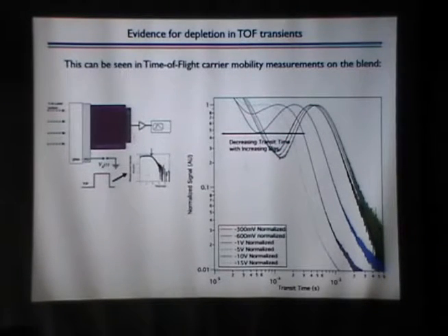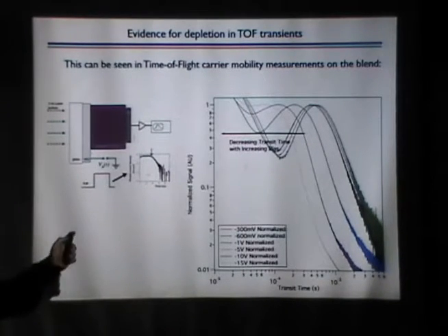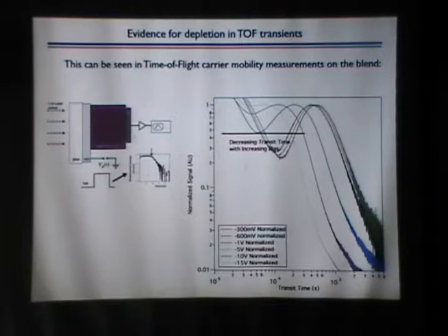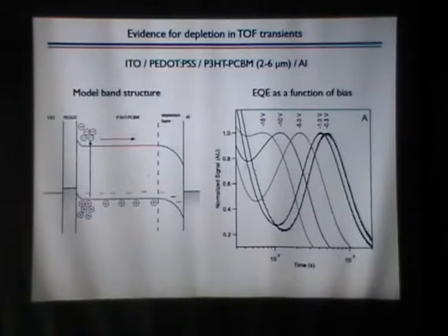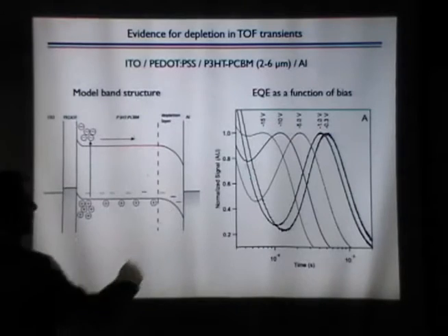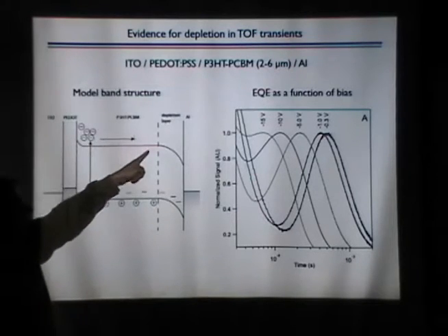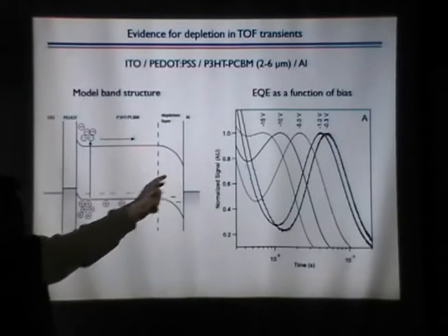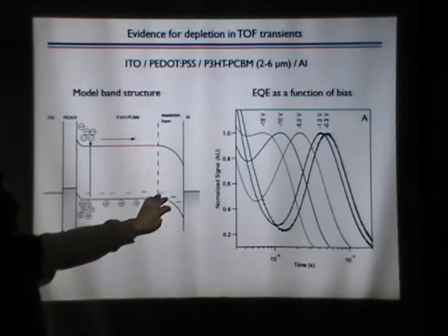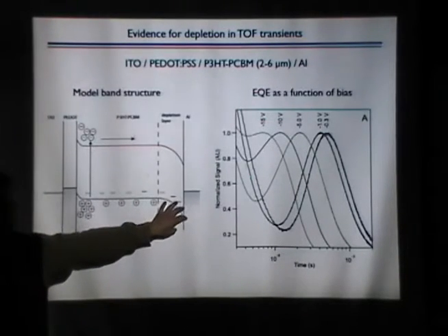At first we looked at that, we did not have a good explanation, but my colleague Jao van de Lagemaat said, aha, this is an indication for band bending in the device. And if we assume that the band structure looks something like this, where here's our Fermi level alignment, here's our two electrodes, under the simple picture we would assume straight lines here, right? But if it's not the case, then what we have is a flat region, and then all the band bending towards the negative electrode. So all the field is here, this is a field-free regime, this is the field.